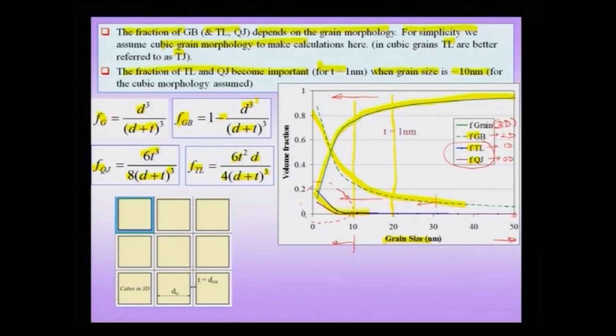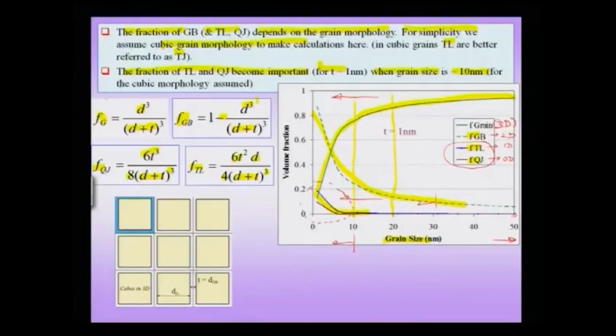And the important point is that these calculations come from assuming a cube morphology and a grain boundary thickness of about 1 nanometer. Then we can write down the fraction of these various entities given by these formulae by a pure geometrical calculation, which is easy to perform. Therefore, I can have the fraction of these entities, and I can calculate how these fractions start to change. The overall trend is that whatever fraction is lost from the grain goes into either the grain boundary, the triple line or the quadruple junction.